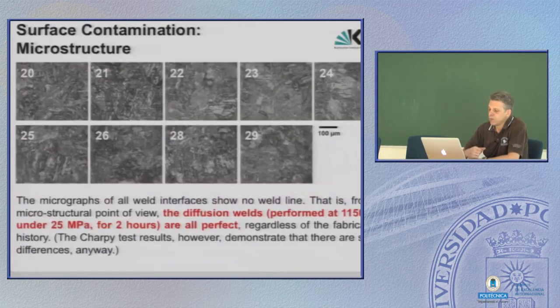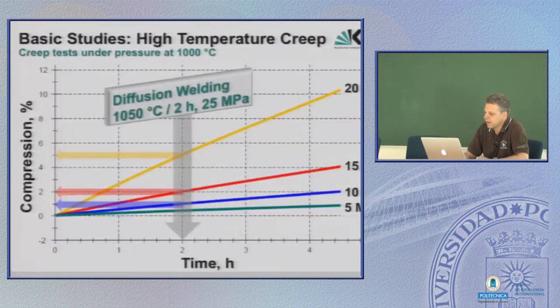Then again, we have compared the weld lines with these higher HIP temperatures, and what you see now is that you see nothing. There is no weld line. This is a perfectly structured Eurofer, and so in principle this was the basis for our further investigations.